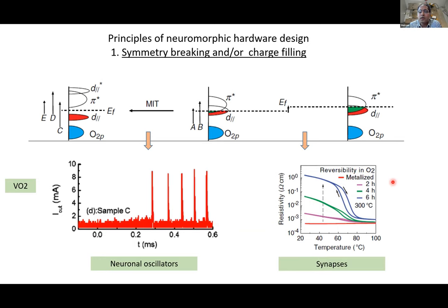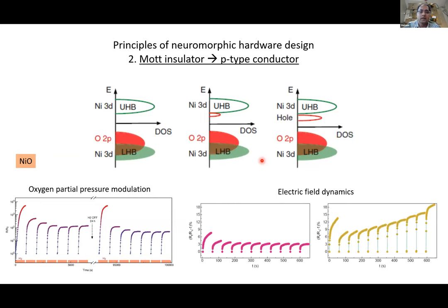And also, very interestingly, you can control the volatility, or in other words, non-volatility. If you introduce charge defects, you can introduce non-volatility, whereas if you have a pristine compound, then you have what's called a threshold switch, where you have hysteresis or short-term memory. So these are a very diverse set of properties that can be obtained with the same material by controlling the crystal chemistry. Now, if you look at NiO, nickel oxide, it's another well-known Mott insulator. Here, the band structure is slightly different. It's called a charge transfer insulator, so you can have excess oxygen that provides hole type conduction. And if you can create metastable defects here, then you can have some really interesting behavior.